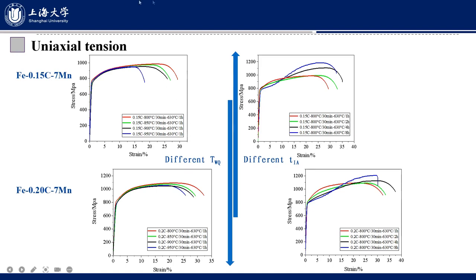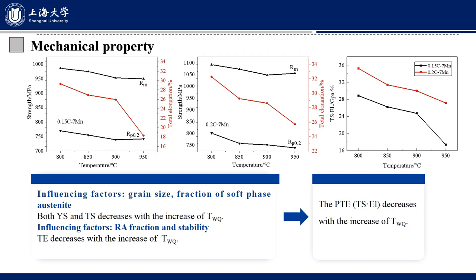It's very interesting that yield point elongation disappears. This slide shows the mechanical property of the steel for different heat treatment conditions, and it's clear that the product of tensile strength and elongation of the steel decreases with the increase of water quenching temperature, and the influencing factors include grain size and fraction of soft phase austenite.